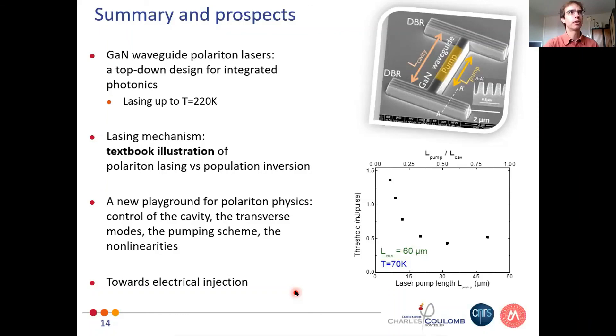Jesus responds: We actually have a PhD student working exactly on this — getting an electrically injected gallium nitride microwire polariton laser. In principle it may seem simpler, but in practice it's not: the whispering gallery mode overlaps with the highly doped regions. Compared to planar structures where we can precisely control thicknesses and injection geometry using everything we know about growth, controlling the exact geometry in microwires is not so easy. What seems simpler in theory is technologically very difficult.